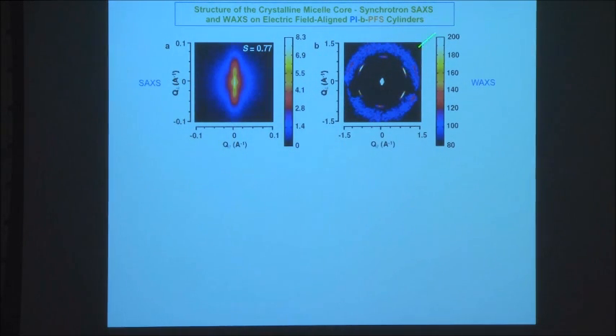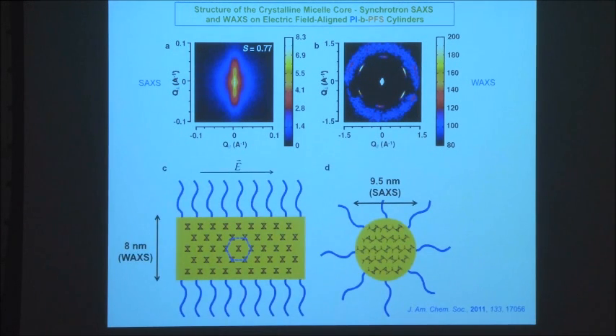And this is the X-ray diffraction of the core of the micelles. And you get a beautiful diffraction pattern. And this has allowed us to actually work out how the chains are packed. And they're actually packed perpendicular to the long axis of the cylinder. So if you do a cross-section, the polymer chains are in a trans-zigzag planar conformation across the cylinder like this. And the structure of the single crystal of the pentamer that I described earlier was vital in allowing us to actually determine this structure here.